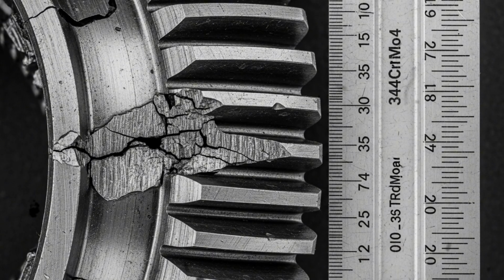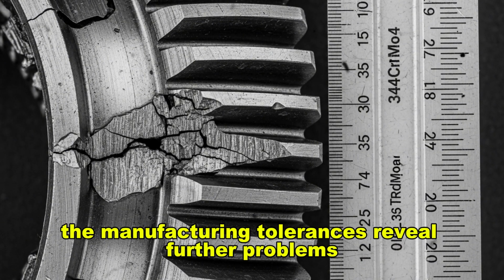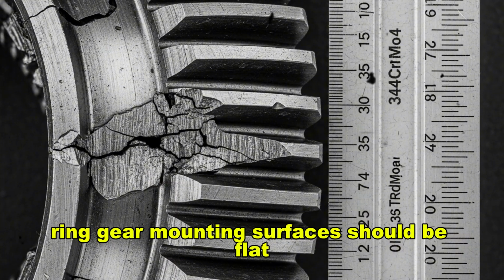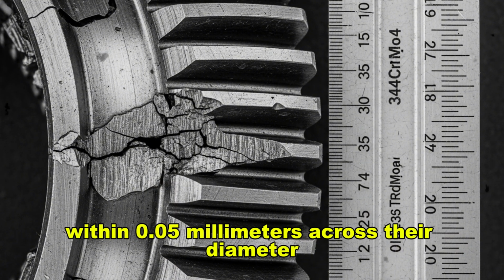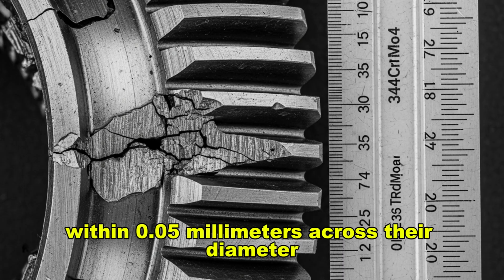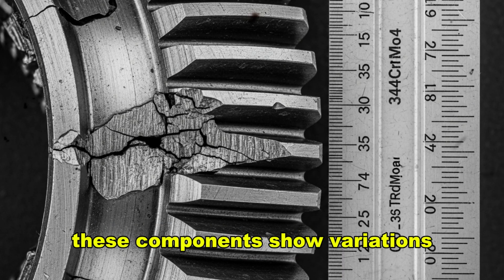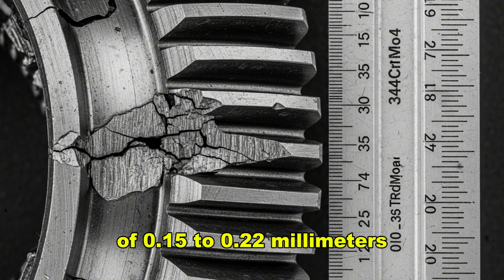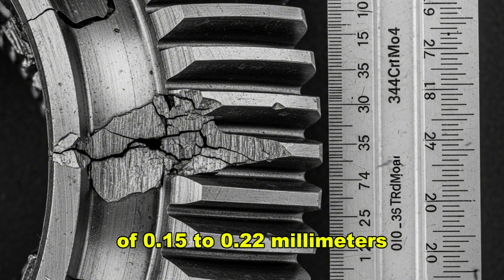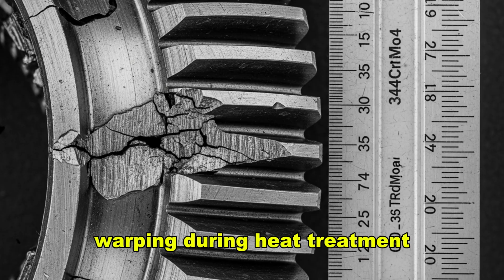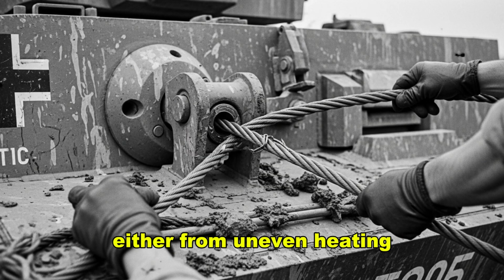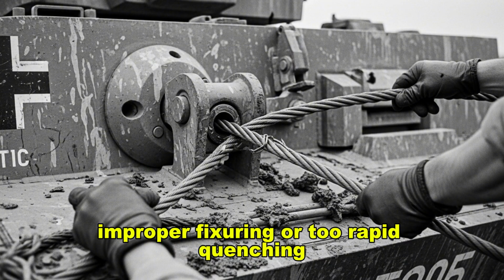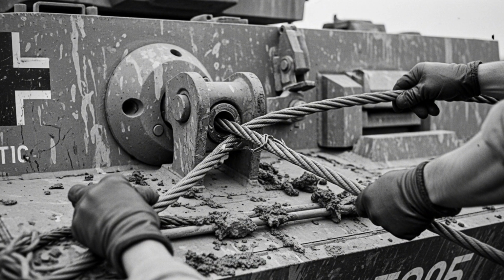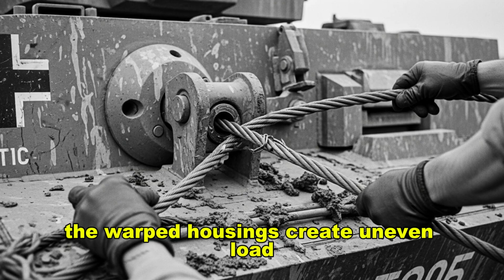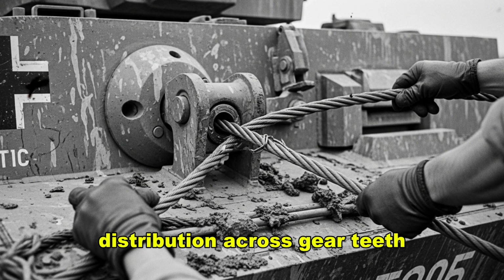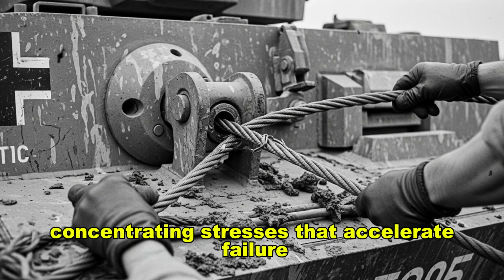The manufacturing tolerances reveal further problems. Ring gear mounting surfaces should be flat within 0.05 millimeters across their diameter. These components show variations of 0.15 to 0.22 millimeters. Such distortion indicates warping during heat treatment, either from uneven heating, improper fixturing, or too rapid quenching. The warped housings create uneven load distribution across gear teeth, concentrating stresses that accelerate failure.